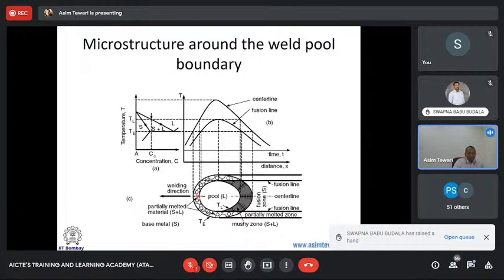So this is the direction of movement of your heat source. This is the pool which is formed. And this weld pool, or liquid melt pool, will have different temperatures at different regions. So this is the fusion line, which is where this is liquid, but outside is not liquid. If you see, the center line temperatures are going like this, and this is how the fusion line temperatures are. You have partially melted regions in between, so this is the partially melted zone. Beyond this, complete melting; beyond this, complete solid. Under this, complete melting. This is the mushy zone, the gap between the liquidus and solidus.